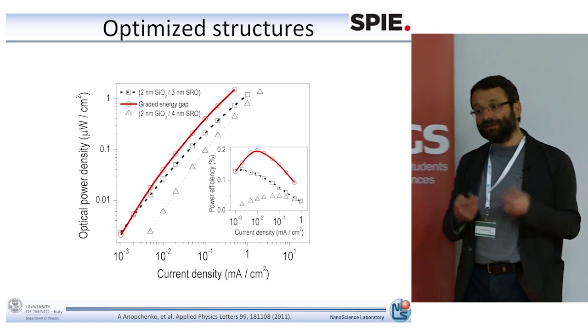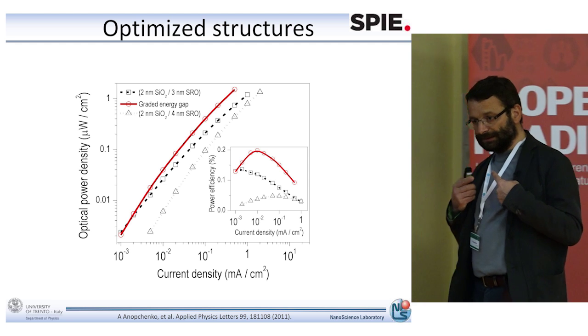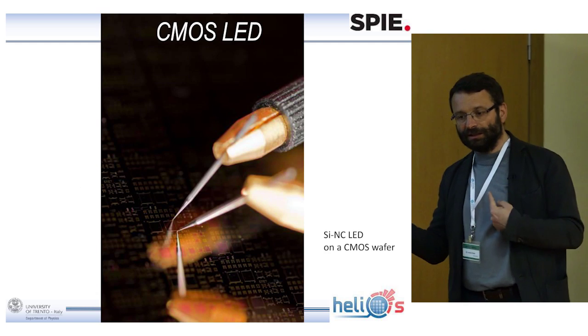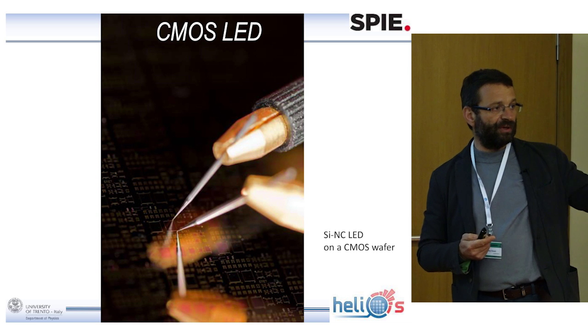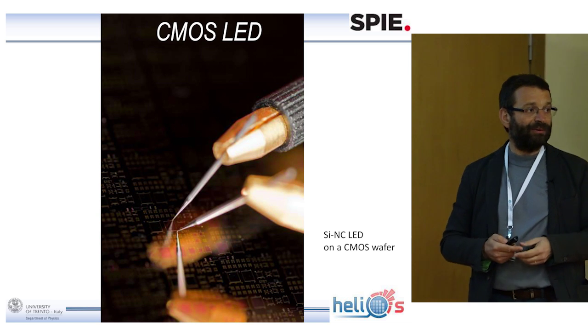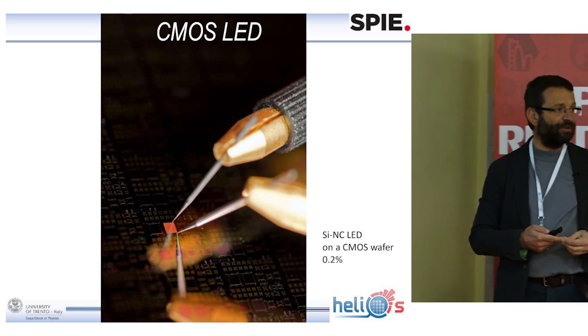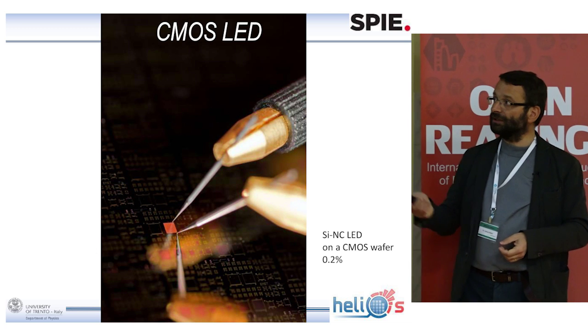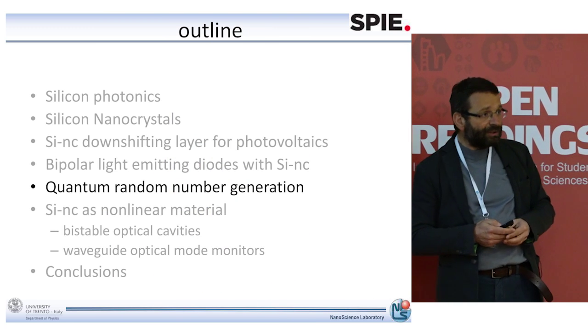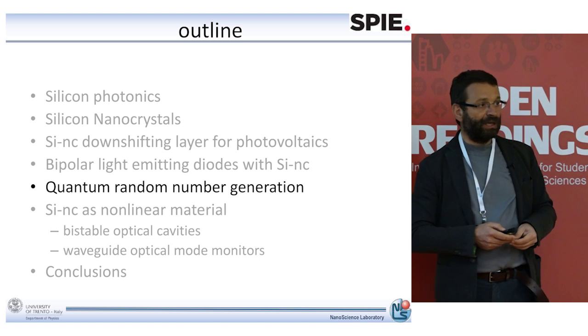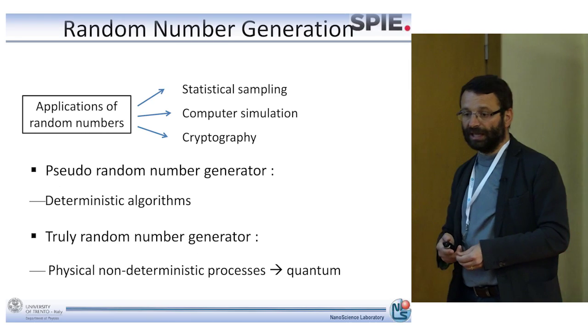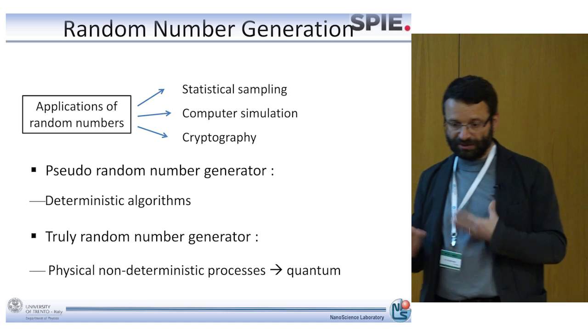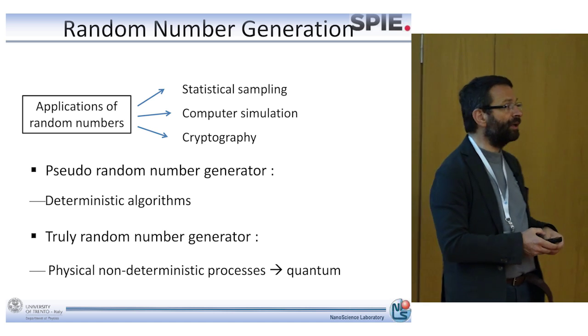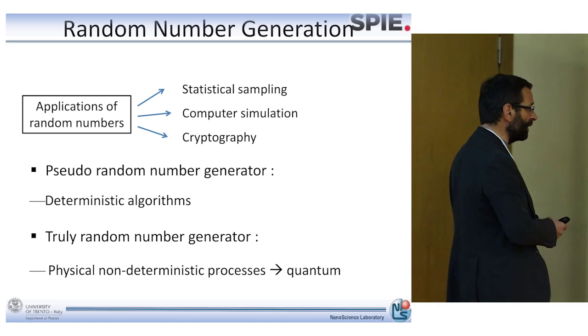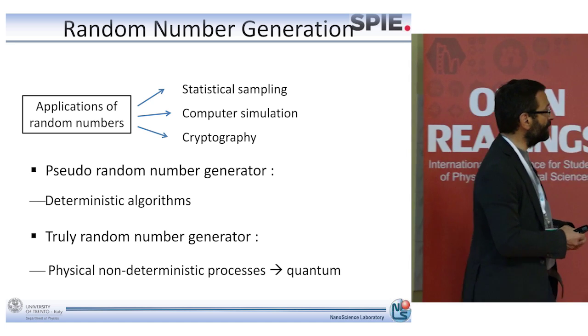So this means that actually the nanocrystals are very interesting material, but are not good for LEDs. Because III-V LEDs have a power efficiency of 30–50%. So these are not comparable. So what can we do with those nanocrystals? Here is an example of an application that we are developing, and actually we are spinning out a company on that, and it's based on the use of the nanocrystal to make a quantum random number generator.